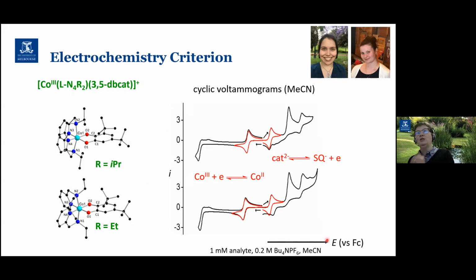This is using the convention that positive potentials go to the right. The first oxidation is the oxidation of the catechol to the semiquinone, quite nicely reversible. And the first reduction is the reduction of the cobalt-3 down to the cobalt-2. So you can see as we go from the isopropyl to the ethyl, the difference in those processes is about 100 millivolts. And we've started calling that parameter delta ox minus red.